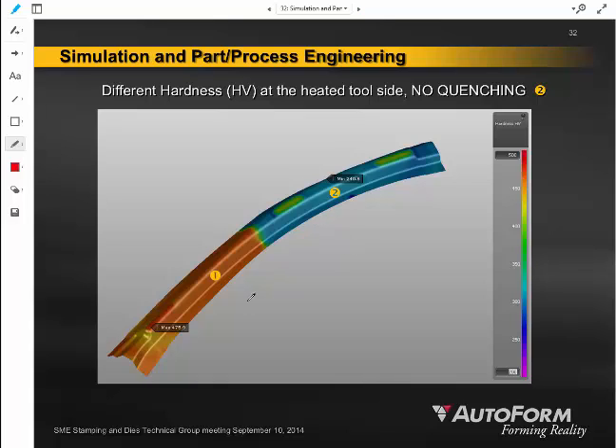And you can see we also will not only measure and try to predict that microstructure, but also show what the hardness of the material is, right? The strength of the material is being measured in terms of Vickers hardness. What is the strength of the material in these areas? And again, where I see this orange coloring, those are materials that, because of their martensite purity, their martensite content, are very high on the hardness scale.